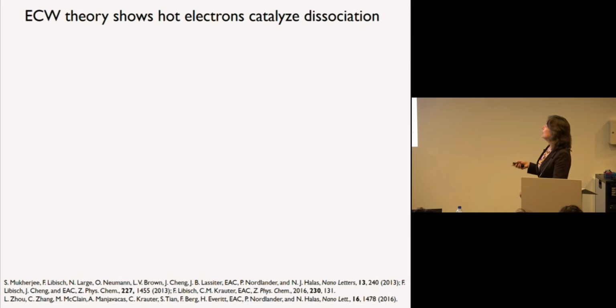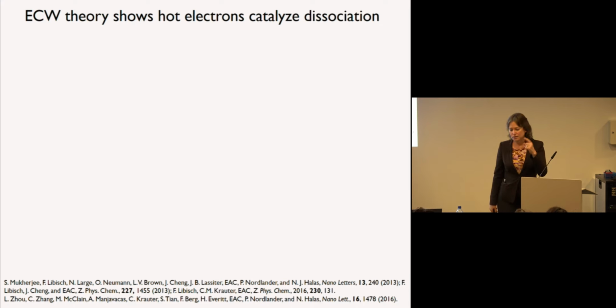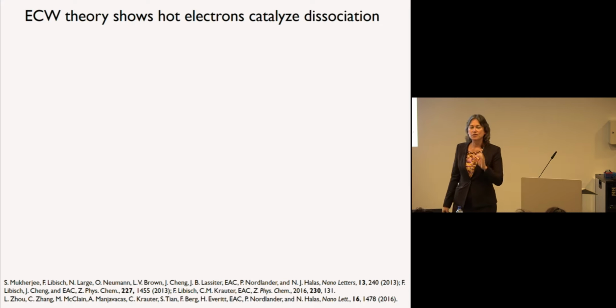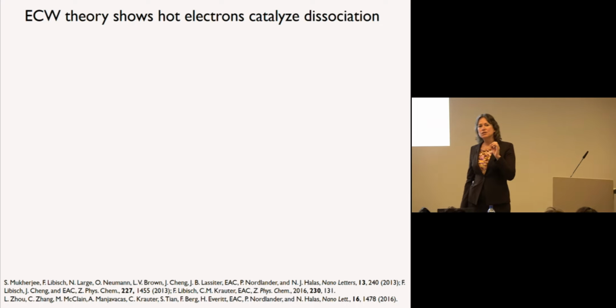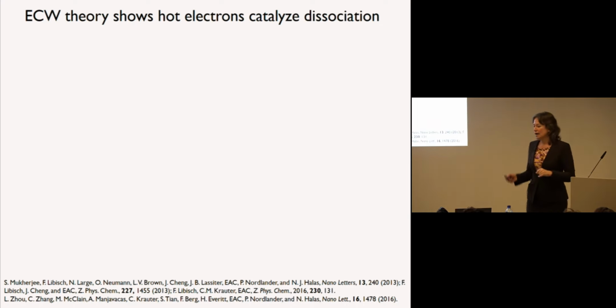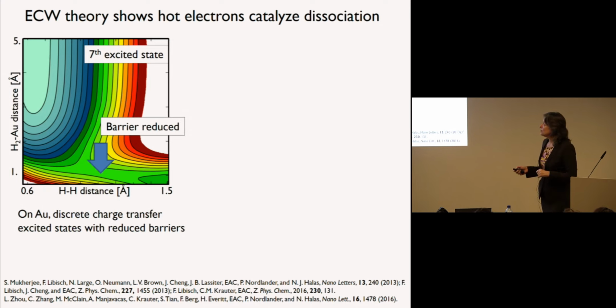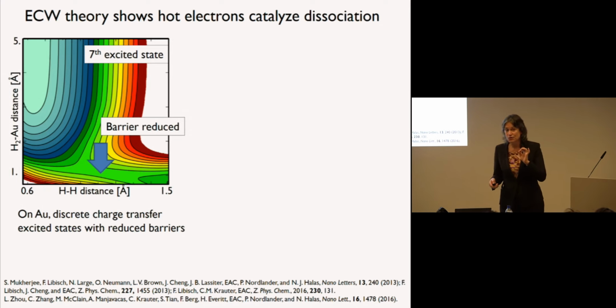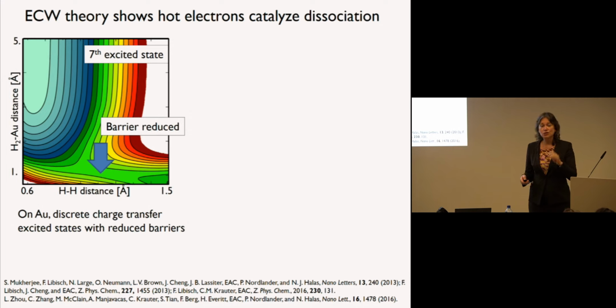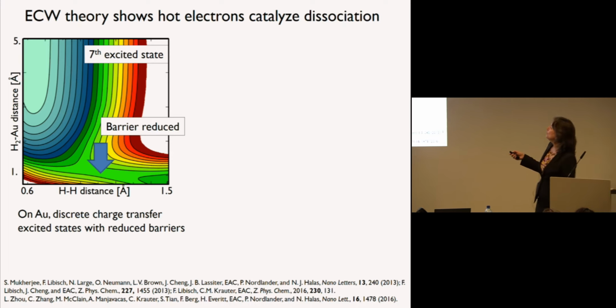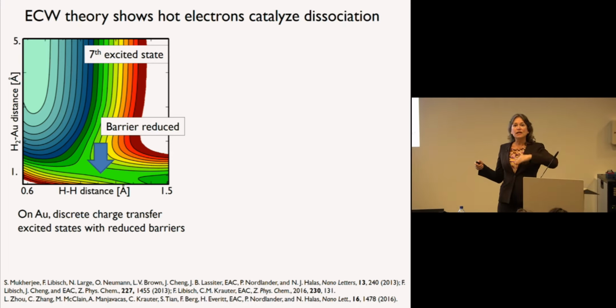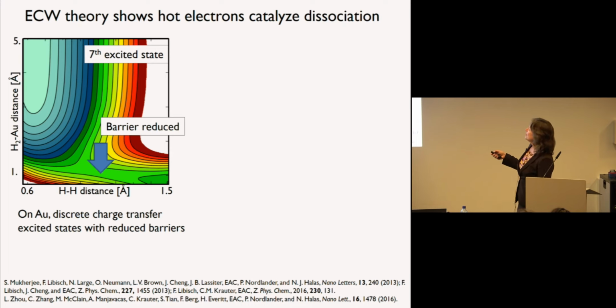So this is showing actually looking at the system that was that first system that Naomi Halas told me about, which is hydrogen dissociation on gold. And I'm going to just show you one potential energy surface. This is for an excited state potential energy surface. The ground state surface does what it should do, which is has a very large barrier. We know that hydrogen doesn't dissociate on gold. But if you look at the excited states that are accessible at the energies of the plasmons, it turns out that the seventh excited state has a barrier that goes down.